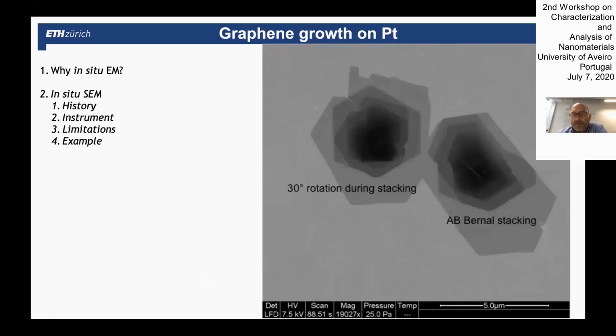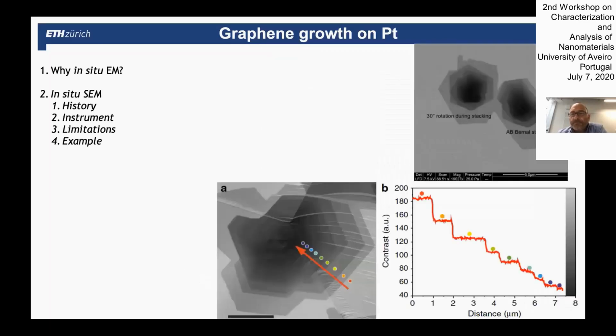And we have some very nice results that I hope will be soon published here about the adlayer formation. And the crazy thing is that we can, in the SEM at 1000 degrees, distinguish the contrast change for each individual layer up to like 7-8 layers in the contrast range that we have available. So it's really an atomically sensitive tool in terms of the coverage of a surface.